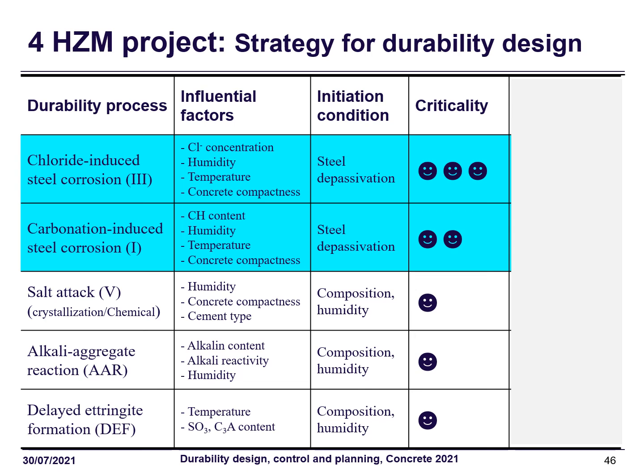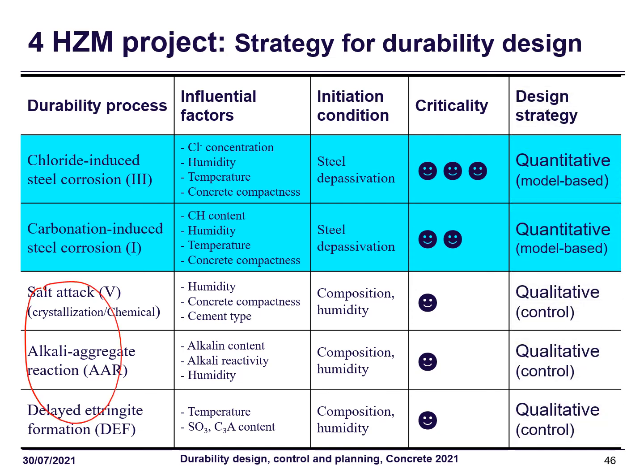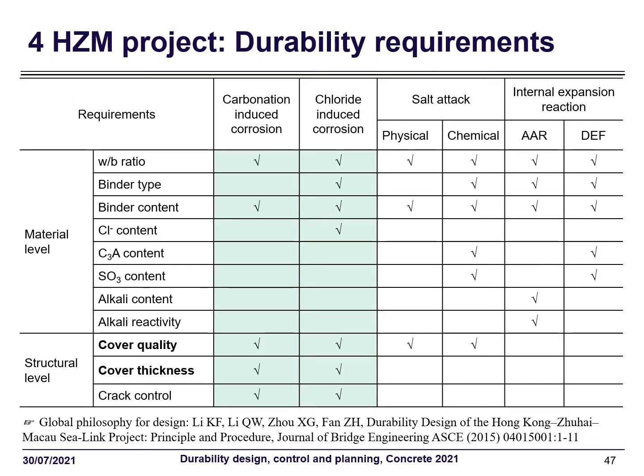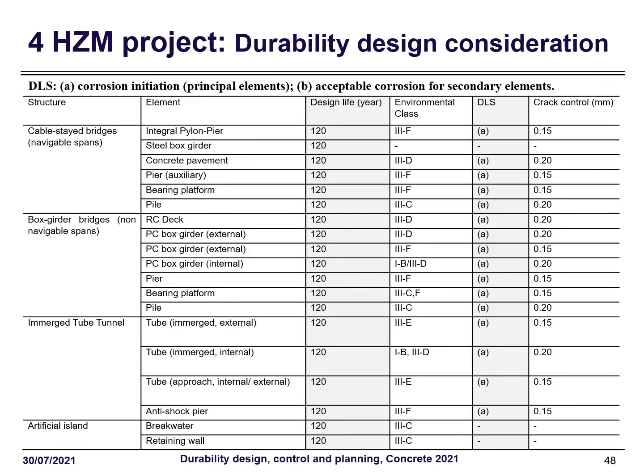The first strategy is to divide all the durability processes into 2 groups. For the low risk groups here, we control the durability risk through the qualitative raw materials control. And for these 2 high risk groups, we can only control the durability risk through quantitative model-based design. Here is the durability requirement prescribed or to be prescribed both on material level and the structural level with respect to the different processes. And if we want to use model-based approach, we need to know the design life, service